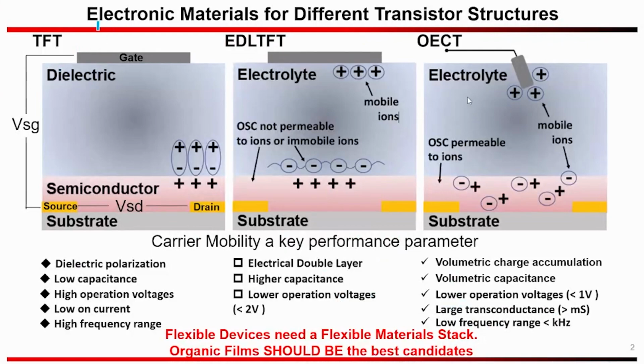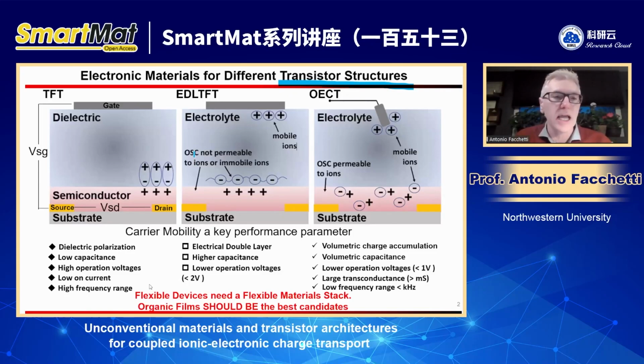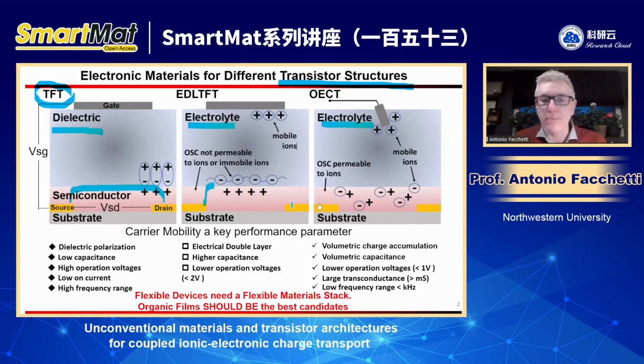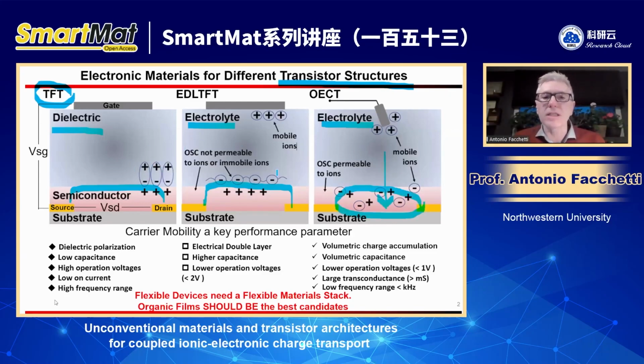What we have been interested in now for several years has been to develop electronic materials for different transistor architectures, going from FET architecture, where the key element is the gate dielectric, which is polarized. So you have charge transport which happens in the semiconductor only at the interface between the dielectric and the semiconductor, or using electrolyte as a polarizing dielectric. And here, the semiconductor is impermeable to ions, or the ions cannot penetrate, and the charge carrier remains interfacial. Or in OECT, the semiconductor is permeable to ions, so the ions can penetrate into the semiconductor. And you have a bulk charge transport, which is associated with a redox chemistry of the semiconductor.